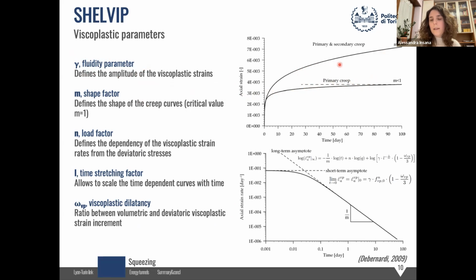If it is bigger than 1, the limit of the axial strain for time tending to infinite tends to infinite, so we can describe also secondary creep. And another interesting thing is that in the plane axial strain rate time, we have a long-term asymptote whose slope is equal to the inverse of m. Then we have n, the load factor, that defines the dependency of the rate of the viscoplastic strain on the deviatoric stresses, a time stretching factor that scales the curve with time, and viscoplastic dilatancy, which is the ratio of volumetric to deviatoric viscoplastic strains.